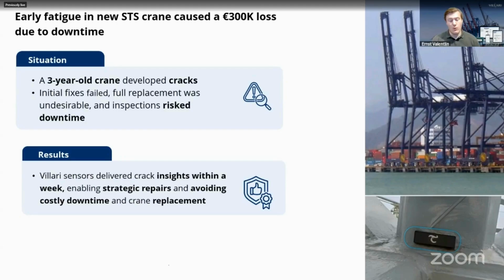that they could then relate to causing the crack growth to happen. With that knowledge and information, they were then able to go back to the drawing board together with the manufacturer and plan the repairs and reinforcements to ensure that that specific behavior would no longer cause these cracks to occur in these locations. And now after that, we are still continuing to monitor them, and this time so far without continuing crack growth.